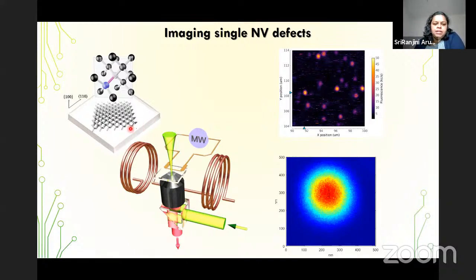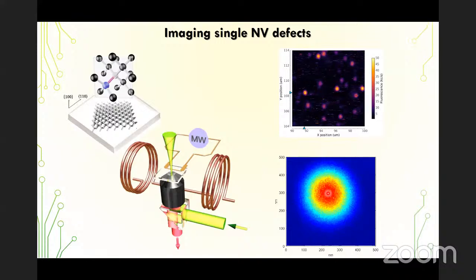This is another schematic in which you can see this is the study of interest. And then you have this NV center kept, you can do both ways. You can have the diamond on the surface and put the molecule on it, or put the molecule and then place the diamond on it. I'll come to that later. So this is a typical NV center. And if you zoom into one of the points, this is how the NV center bright fluorescent spot is. Each spot you can see under the microscope.